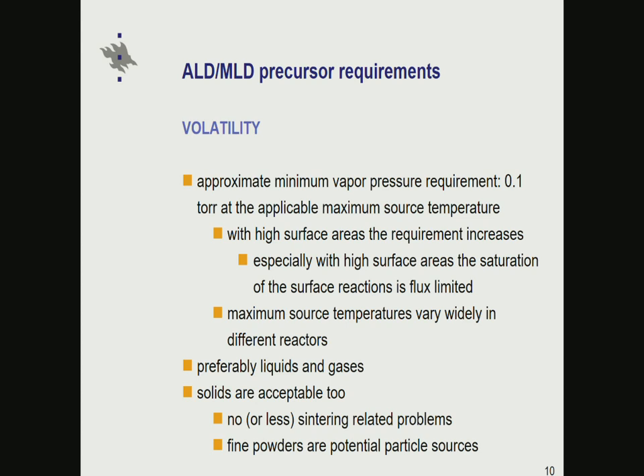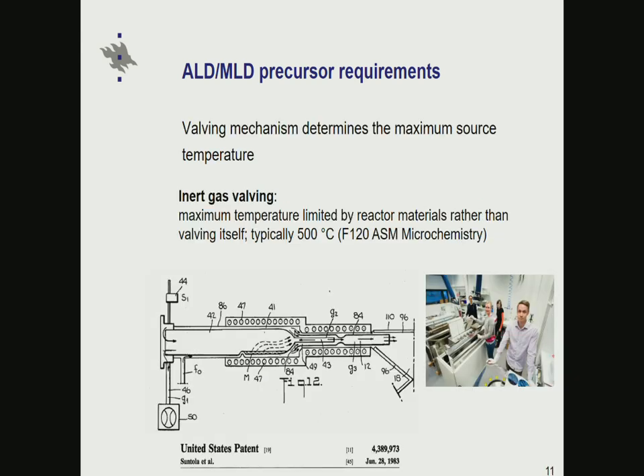So there is sintering, and also the fact that if your solid consists of very small particles, these may be transported with the gases from the sources towards the substrate, even if we are working at about 5 millibar or so, and there they could create defects. So the valving mechanism is very critical for that.